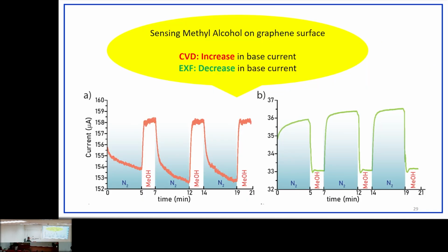Now I'm just sensing methanol molecules, and I know that methanol molecules would lead to an increase. You see, here we have just nitrogen, and when methanol comes, there is an increase in the base current. Again, I'm cleaning the surface, then whenever I send methanol molecules, there is an increase. So this one is for CVD graphene. If I'm using perfect, almost perfect graphene surfaces as a sensing platform, I see an increase.